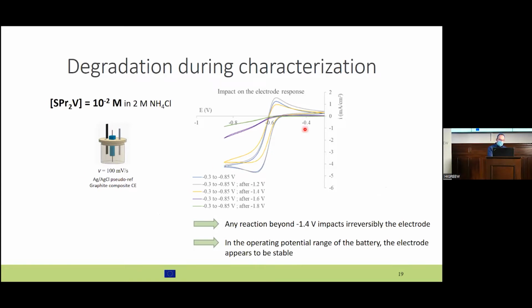electrochemical reaction. This is an example we measured recently, where we are cycling with the microfibers in an electrolyte with halogen. And depending on the condition of the cycling, we see that there is a degradation of the electrochemical signal. So we know that the long-term stability is important.